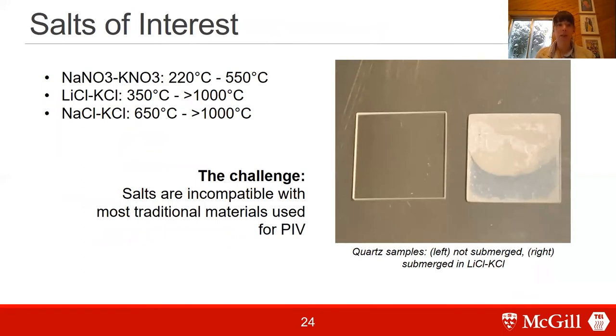And so everything that we've been doing in terms of understanding heat transfer in molten salts has relied on computational models. The reason is that molten salts are typically incompatible with almost all traditional materials that are used for particle image velocimetry, particularly at the high temperatures that we're considering. If you look at, for example, a quartz sample, you can see on the left here an intact quartz sample, and this is a quartz sample after we've immersed it in lithium potassium chloride at elevated temperatures. You can see how the chlorides are really attacking the quartz sample. So we need to manage the incompatibility of the molten salts with a lot of the PIV materials, and we're searching for alternate materials to be used and new ways of applying particle image velocimetry. This is really the very first demonstration of PIV in molten salts.